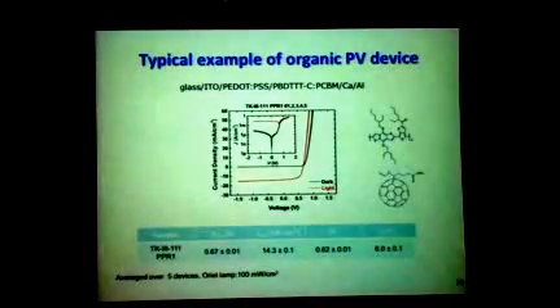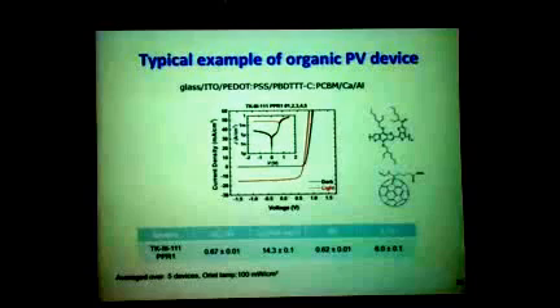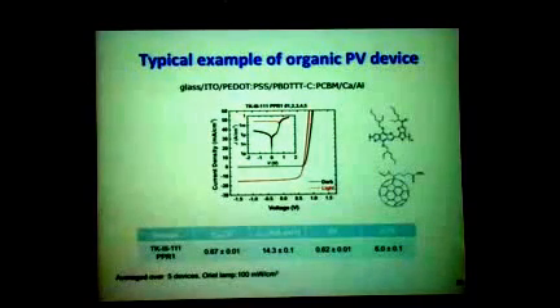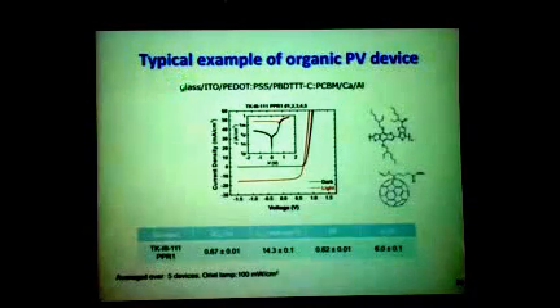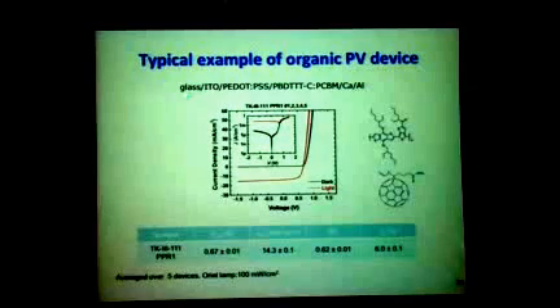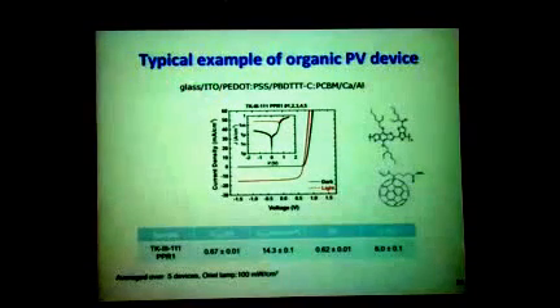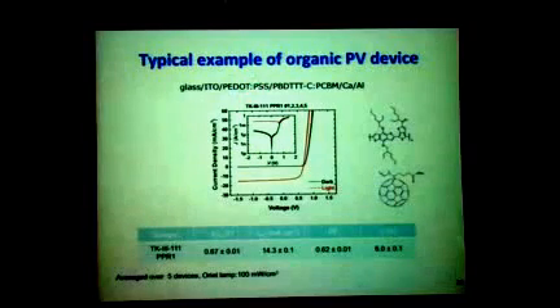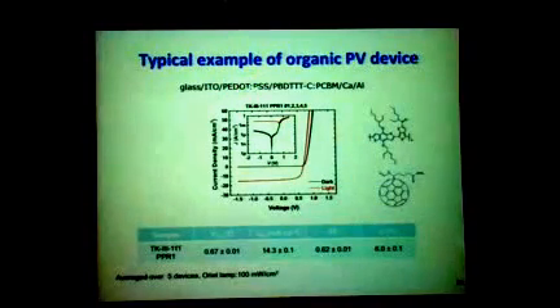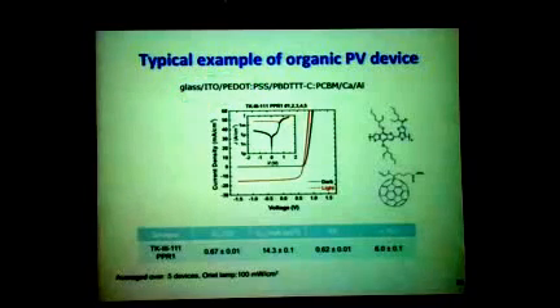Here's the first example of a typical organic solar cell. Like for OLEDs, we start with an ITO-coated glass slide, which here is coated with a conducting polymer that has a work function of the order of 5 eV, and that acts as the hole collecting electrode.